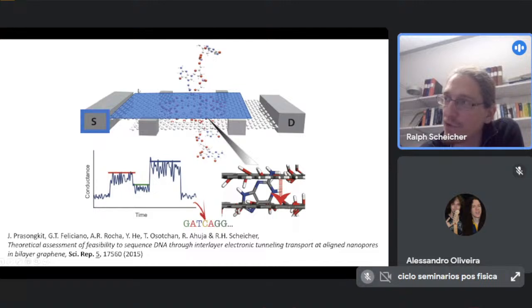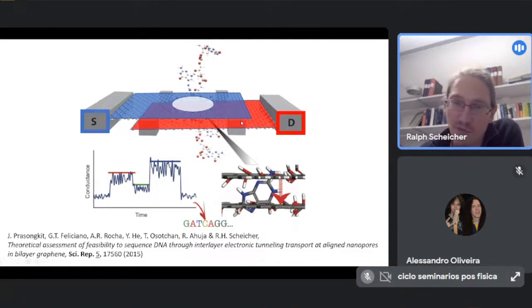So again, here's this one graphene sheet representing our source electrode, and we have a pore inside it. And then we have another graphene sheet underneath it, stacked by a distance of maybe just around 3 to 4 angstrom, acting as the drain electrode, and also has a nanopore that is aligned with the top one. And so if the DNA is now moving through these 2 aligned nanopores, what it is doing effectively is it couples the upper layer graphene, the source electrode, to the lower layer graphene, the drain electrode. So you have some coupling already before, but when the DNA is moving through it, it couples much better. And actually, the distance between the graphene sheets is such that it really perfectly fits basically one DNA base inside there.